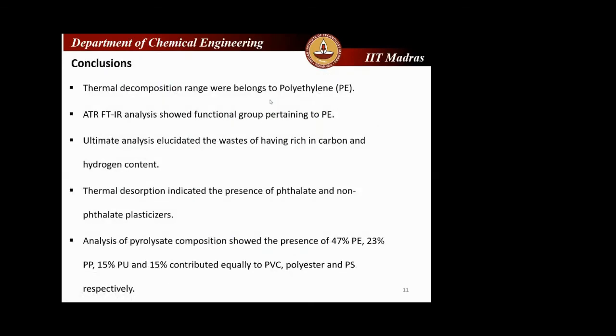Coming to conclusions, in the thermal decomposition range all are belonging to polyethylene, and the ATR-FTIR analysis also confirmed polyethylene, and the ultimate analysis elucidated that these are rich in carbon and hydrogen content. In thermal desorption, I also observed some phthalate compounds, which are added to plastic while manufacturing to give the desired product.